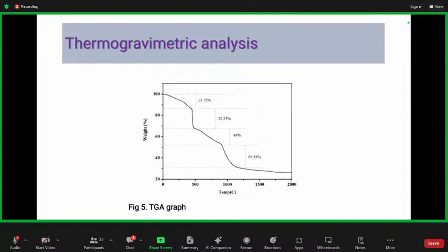So water molecules do not remain after 200 degrees Celsius. Is your TGA graph analyzed or manipulated? It is actually manipulated maybe. See, even water of crystallization goes below 100, up to 100 degrees Celsius. Water of crystallization goes up to 200 degrees Celsius. Thereafter, no water molecules remain in the compound. But you are showing that water molecules are lost around 400, 500 something temperature. At this temperature, no water molecules will remain. So please check this.